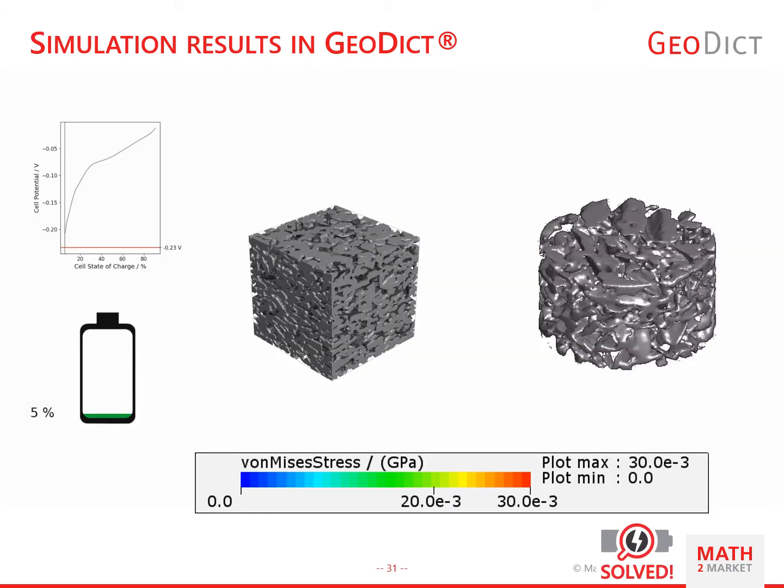In the Solve project, we had the unique opportunity to compare our simulation results with experimental results of the ETH in Zurich. We looked at the swelling of the active material during lithium intercalation. The ETH in Zurich did electrochemical in situ measurements of the charging of active material, while at the same time they took time-resolved, high-resolution micro-CT scans of the same material. These measurements allowed us to compare the swelling of the active material throughout the entire state of charge range.